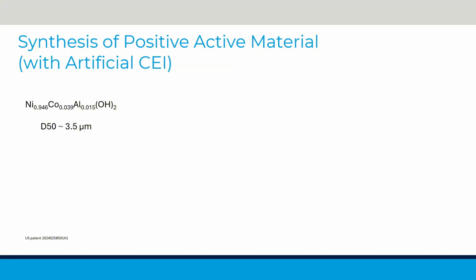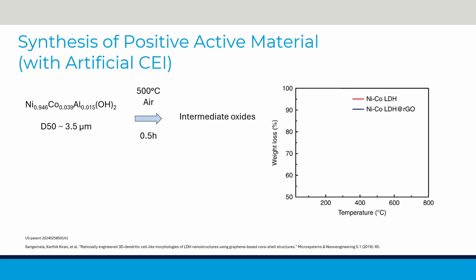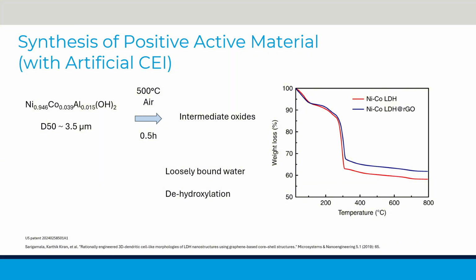Nickel-cobalt-aluminum hydroxide particles with selected diameter are used as the precursor. It's heated to 500 degrees Celsius for half an hour in oxidative condition. During this step, thermal decomposition occurs. The weight loss is understood to be a stepwise loss of loosely bound water and dehydroxylation.